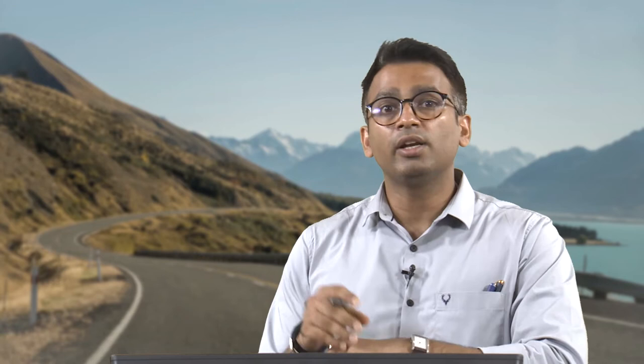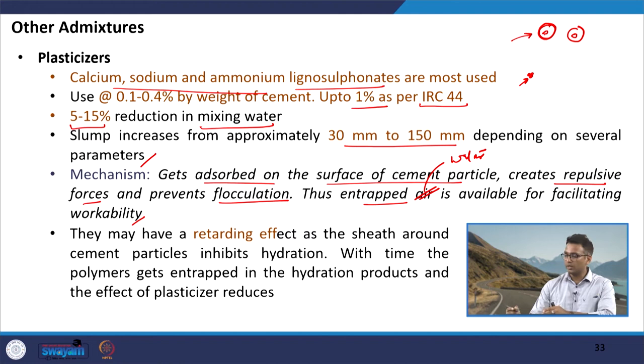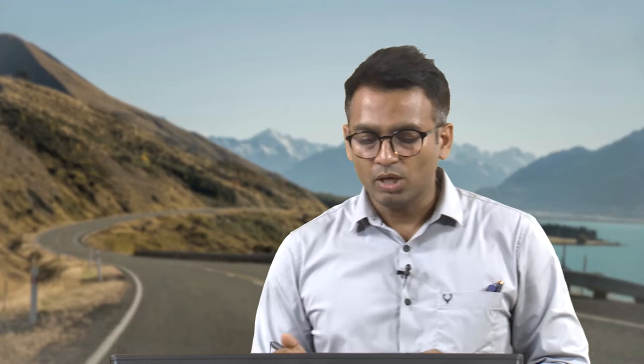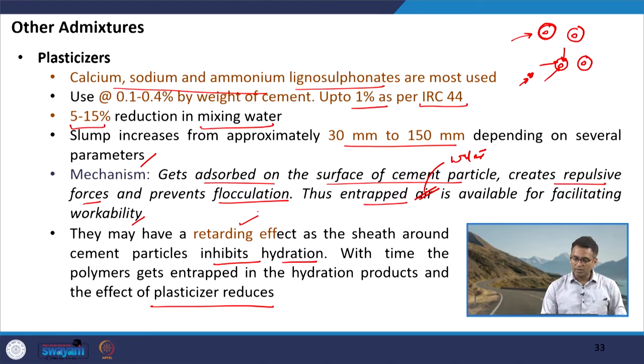Plasticizers can also have a retarding effect. There is another material — the plasticizer — adsorbed over the cement particle, which prevents water from readily interacting with the particle and initiating hydration. This sheath created over the cement particle inhibits hydration. With time, the polymers these materials are made of get entrapped in the hydration products and hydration eventually initiates. So initial strength gain will be slow, but hydration will proceed after some time.